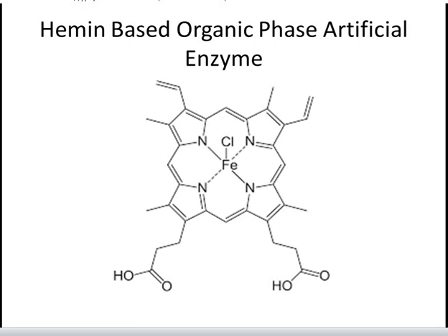At the same time, this electrode exhibited higher electrocatalytic ability toward tert-butyl hydroperoxide than the pure hemin model electrode. The biosensor can reach 95% of the steady state current in about 10 plus or minus 2 seconds.